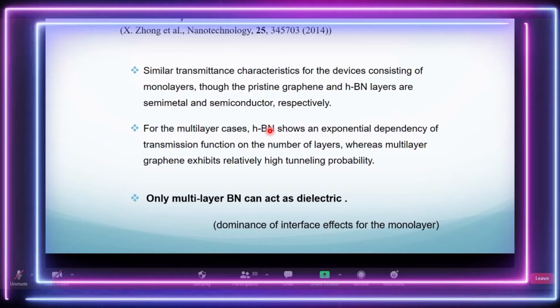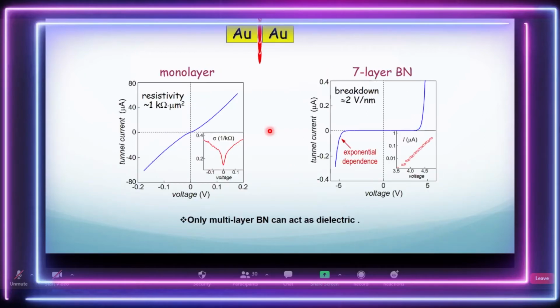So we published this paper, and as you know, people of course read it, and then come back with their experimental results. And it's just a beautiful thing. Like I said, boron nitride has a gap. But what we found in the monolayer case is, like graphene, ohmic-like conduction. And this is an experimentalist colleague, who did the experiment for monolayer boron nitride. And you can see here there is a slight plateau, but more or less it is ohmic-like conduction.